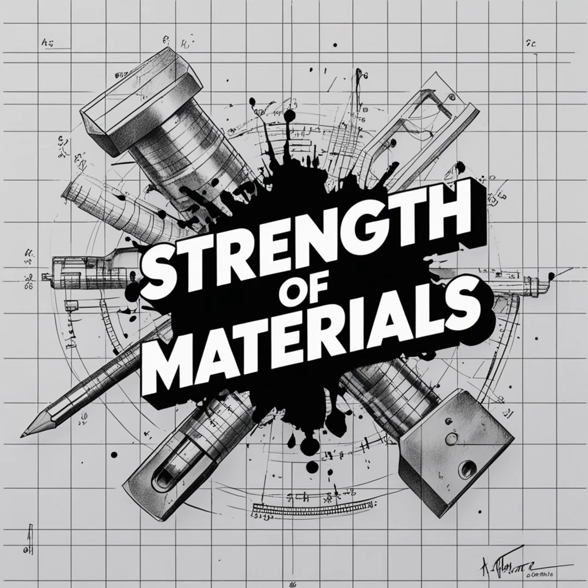To truly appreciate the genius of the J integral, we have to look back at the historical limitations of early fracture mechanics. In the mid-20th century, we had the Williams solution and linear elastic fracture mechanics. These relied on a parameter called K, the stress intensity factor. Okay, K? But K came with a massive restrictive assumption: small-scale yielding. Small-scale yielding, meaning the little zone of plastic, permanent deformation, right at the very tip of the crack, has to be absolutely tiny compared to the overall size of the steel beam or part. The vast majority of the part has to remain perfectly springy and elastic.